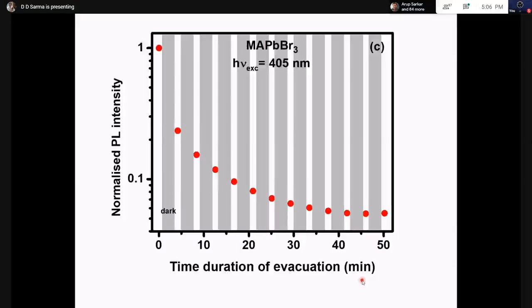Okay, having understood that, now how do I do my experiment? Because I need to have photons go in, but the photons will get absorbed at the surface. I need to evacuate to be able to change the temperature. But if I evacuate, my passivation goes. I need to somehow do the absorption deep inside the material so that even if I evacuate, which will affect near the surface, it will not affect my absorption and photoluminescence process.